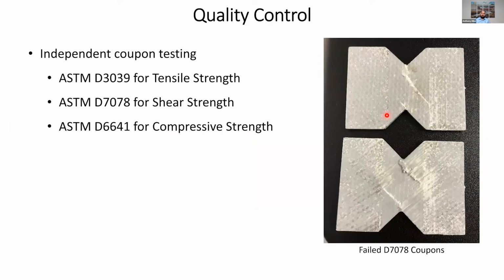Another thing that we still work on with DOTs is that we have a quality control plan, and that is required by the DOTs. And for Grist Mill, for example, we did all 3 of these tests. We did panels separately on the day of the infusion of the girders, using representative layups of the bottom flange, and we did D3039 for tensile strength. We did a representative layup of the web and did D7078 and got the shear strength. And then we did a representative of the top flange and did D6641.